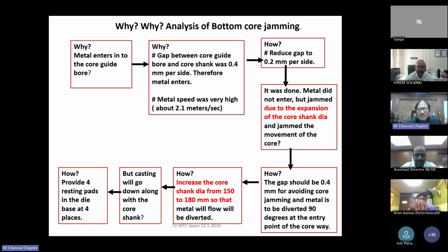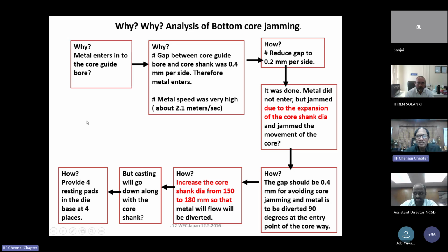Again, we followed a method of why-why analysis for the bottom core jamming. It's our practice. Metal enters into the core gate, the phenomenon. Why? The gap between the bore and core shank was 0.4. If the gap is within 0.2, 0.1, metal doesn't enter. If it is 0.4, it enters. And we tried to reduce the gap to 0.2 mm per side near the new core. But when we tried this, because of the heat, the shank expands and the bottom core jams because of the expansion of the shank of the core. So 0.2 is too tight.